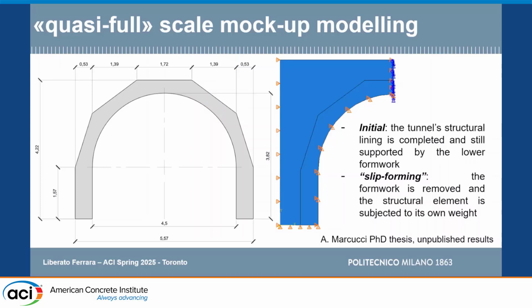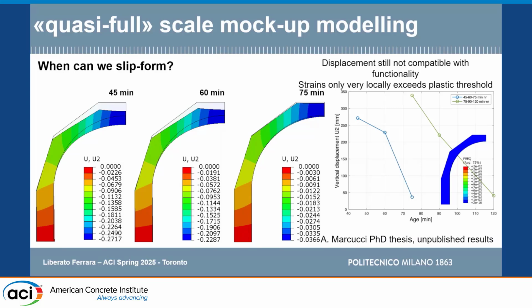So in the beginning, everything was frozen. And at a certain point, we removed these constraints here on the inner vault of the lining, just to simulate the fact that the formwork is slipping, and so there is no longer a support. And as a matter of fact, we realized that, for example, in the very early minutes that we checked, up to 1 hour, we still have a very, very huge deflection, even if we never exceed the plastic strains except locally. So the lining is globally safe, but still experiences a deformation which is absolutely not compatible for the functionality of the technology. At 75 minutes, we just experienced a few centimeters, which is okay.